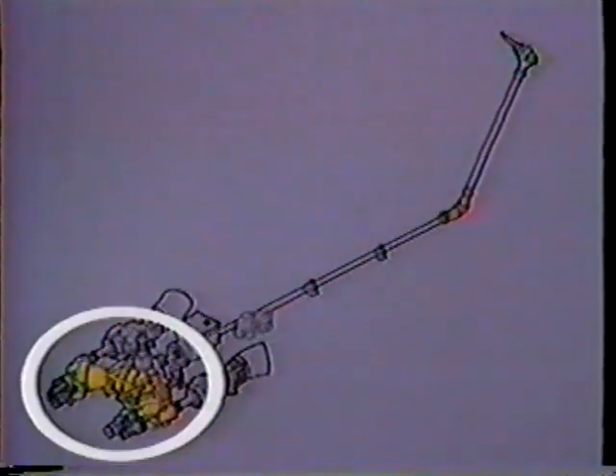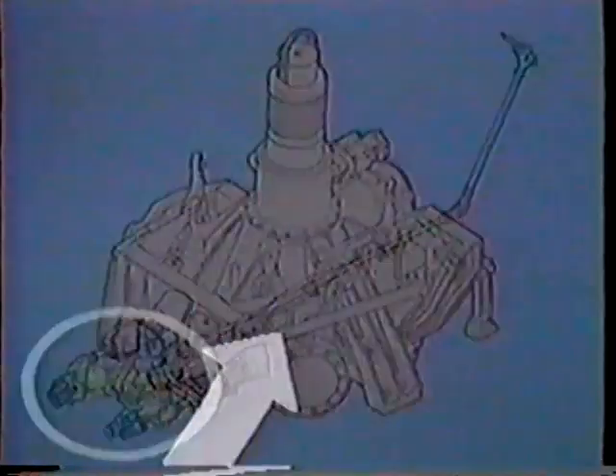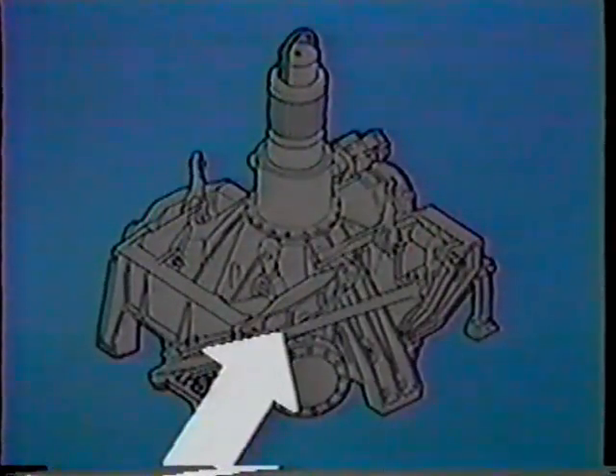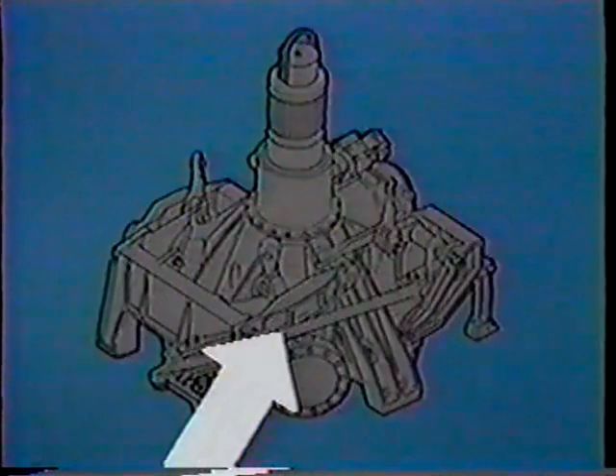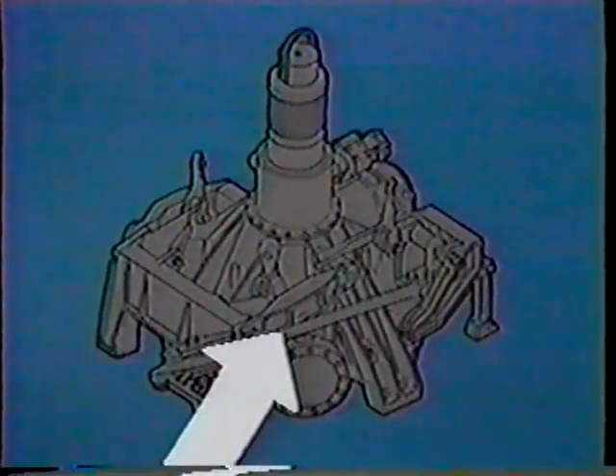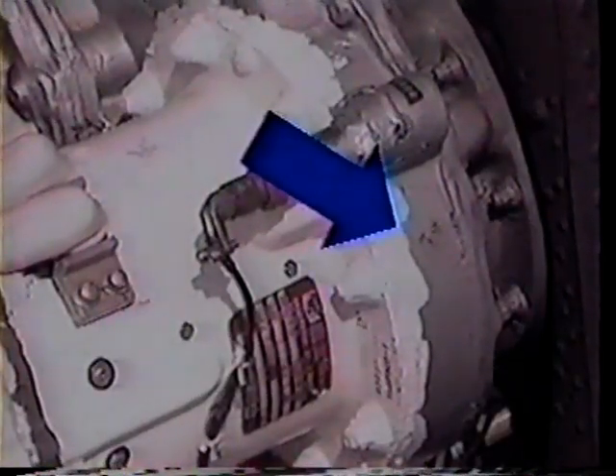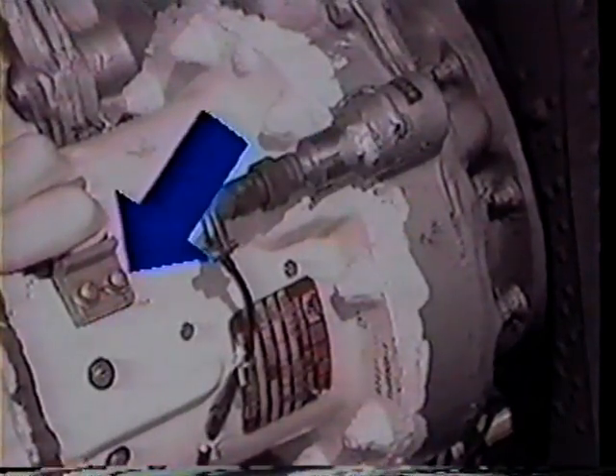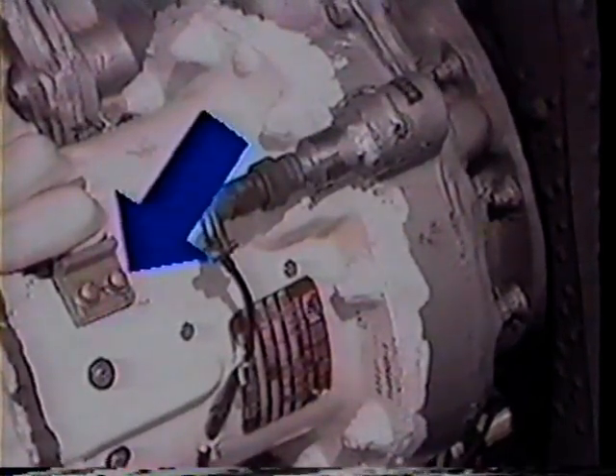AVSCOM and Sikorsky have incorporated many changes to the gearboxes to reduce corrosion. One of these changes is the application of clear polyurethane sprayed on the input module. Other changes include filling of voids to eliminate places where water can get trapped, surrounding fasteners with sealant, painting over seam caulking, and plating of fasteners with cadmium metal.